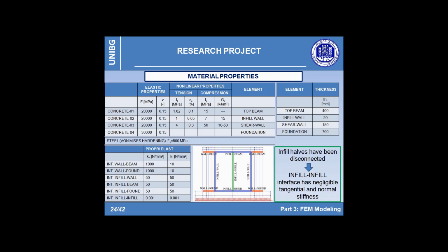As also reported in the previous slide, the interface mechanical properties have been calibrated based on the experimental measurements. Interface elements have been provided between each structural wall and the respective top beam and foundation. A reduced value for the tangential stiffness has been calibrated according to a stress-displacement relationship, taking into account the double action of the longitudinal bars. In this way, it was possible to reproduce in a simplified way the horizontal sliding observed in correspondence of the constructional joints.